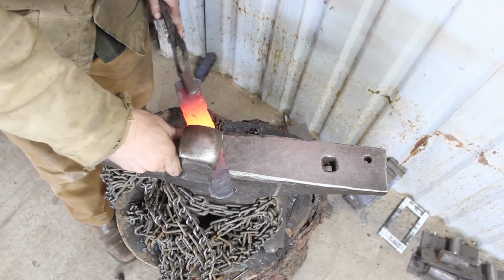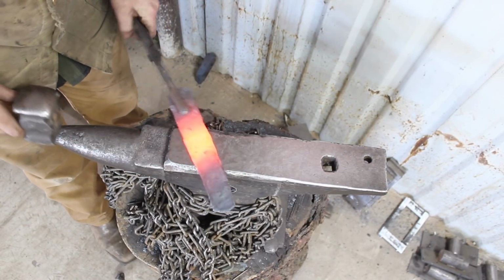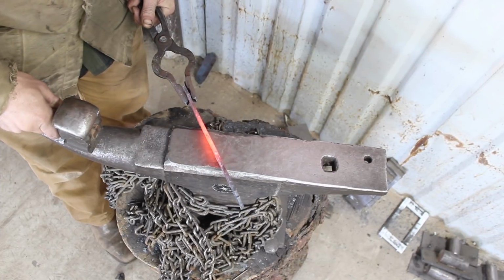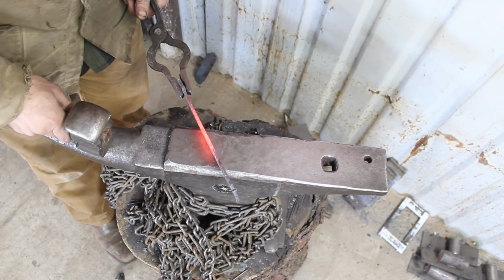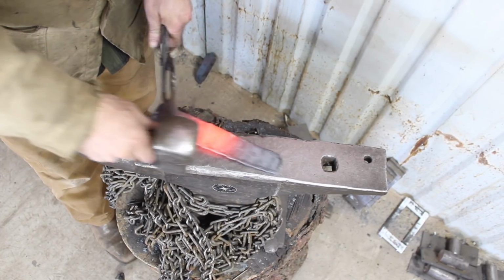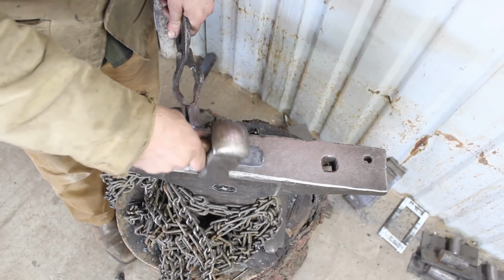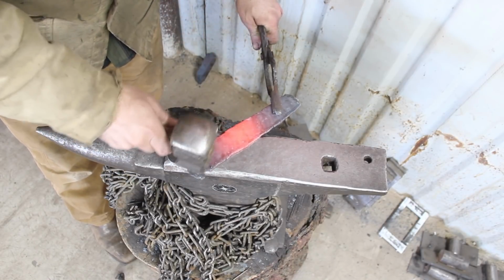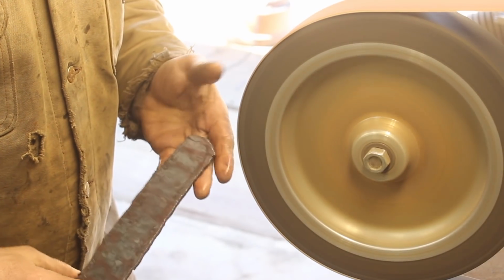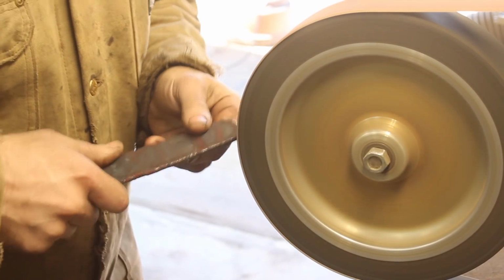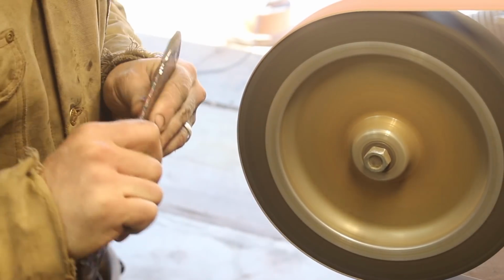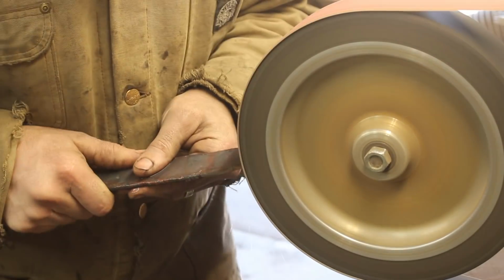I should have enough material left here to get the knife that I need out of this, but what you don't see is something that I wasn't recording, but I actually had some copper squirt out of the billet, which was kind of interesting. Molten copper, you know, at a bright red or orange heat. So it's kind of dubious as to whether we're going to have what we need to have in here, but it appears to be somewhat solid.